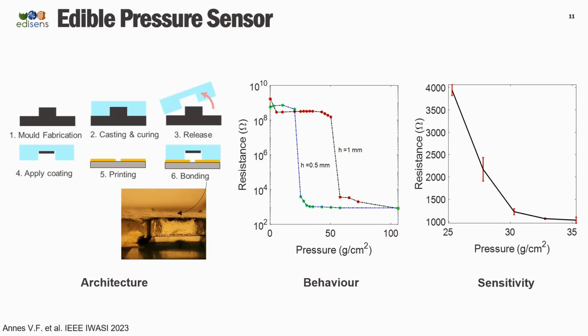So as you can see here, for different heights of the microstructure, at some point you have conduction, which means the coating is in touch with the gold electrodes, and then as you increase the pressure, you have not such a high sensitivity, but a small response to pressure.